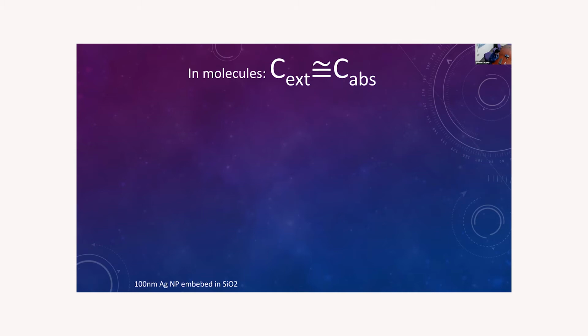To take this into account, for example, let's think about molecules. In molecules, the extinction coefficient is mostly the same as the absorption coefficient. Why? Because molecules are very small, and the third contribution, that would be the scattering, is negligible. But in the case of nanoparticles, we have to take into account the absorption, but also the scattering, the dispersion of the light due to the nanoparticle.